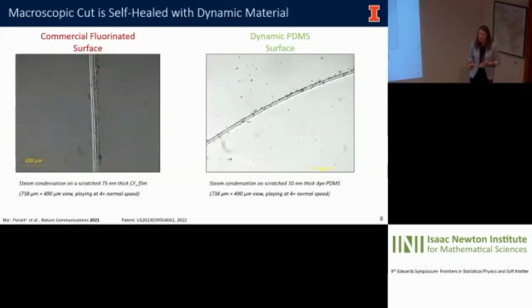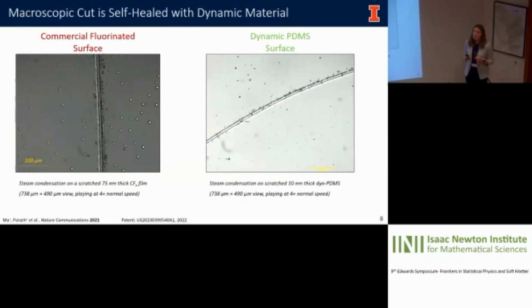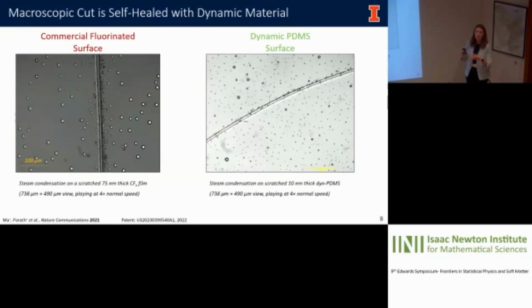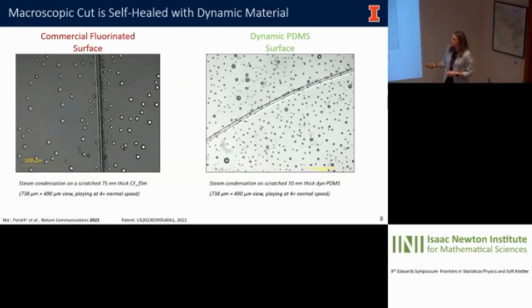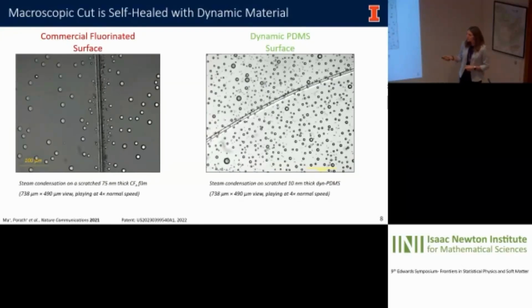So we tested it and we did a macroscopic cut on the fluorinated surface and on the dynamic PDMS surface. And this is in a humidity chamber. What we're looking for is the condensation of water droplets and their coalescence so that they can slide off of the surface easily. What you see is that the cut pins the droplets on the surface and is therefore not as efficient, whereas the droplets on the PDMS are able to go even over the cut, meaning that the polymer has healed into the cut space.